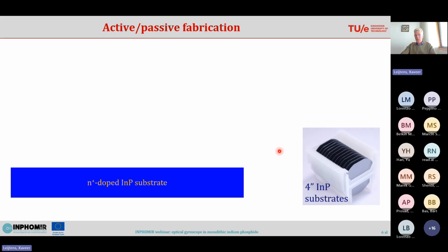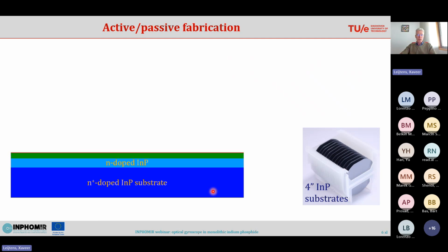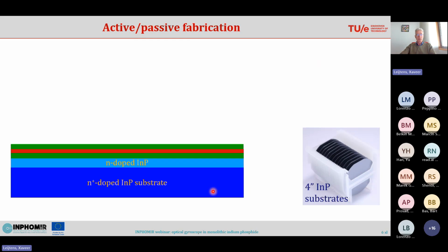So how does this work? These indium phosphide substrates, you can just buy them. So we buy the 4-inch indium phosphide substrate. This is a schematic of the cross section of such a wafer. They are put into the MOVPE reactor, and we first grow an n-doped indium phosphide layer, and then we grow high-index material. We grow multi-quantum wells. The red part here is multi-quantum wells. We grow the p-doped indium phosphide because we need a PIN diode to drive the laser.